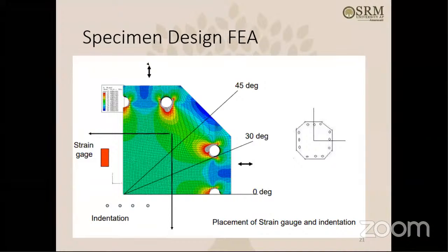So initially what we did is we did some FEA analysis on the specimen, and then designed the specimen like this octagonal shape specimen with all these holes for the clamping like this. So it was designed in FEA, and then we manufactured the specimens for different materials.